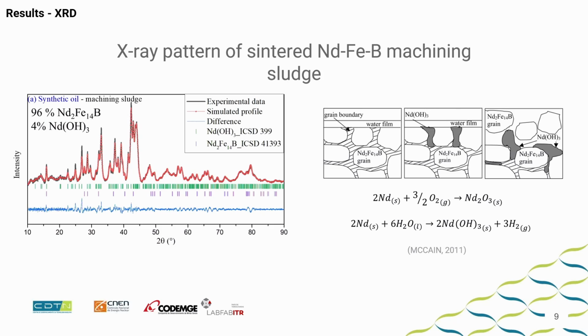The first result here, the X-ray diffraction, partly shows that this residue from the grinding machine has almost 96% of the 2-14-1 phase of this permanent magnet. This is very important, this high purity of this phase, because we need this residue to reuse in this chemical route to produce the new permanent magnets.